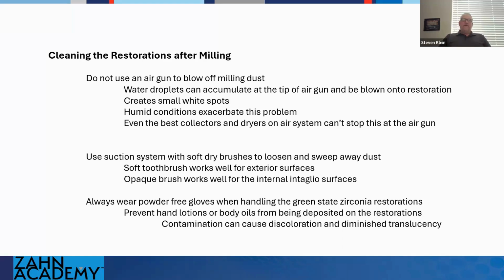What is ideal is to go ahead and use your suction system with soft, dry brushes. All you need to do is loosen it up and let that suction take it away. One of the best is a soft toothbrush. That works great for the exterior areas of the whole crown or bridge. And an opaque brush works super for the intaglio surface. It gets down in there fine, and it's stiff enough that it'll help sweep out any of that dust. And it only adds a couple extra seconds at most, if any, to that process of either blowing it or brushing it off.